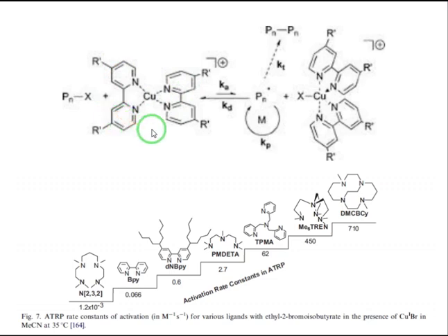Depending on the type of solvent, we can change this complexing ligand to perform the polymerization reaction in different solvents. And you see that the basic idea, this clever idea of detaching the halogen at the end of the polymer chain to let the polymerization progress continue, will help us to control the polymerization reaction.